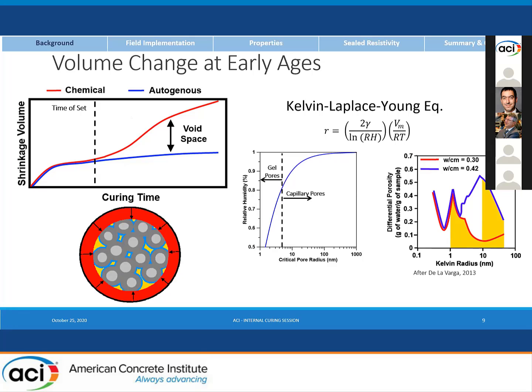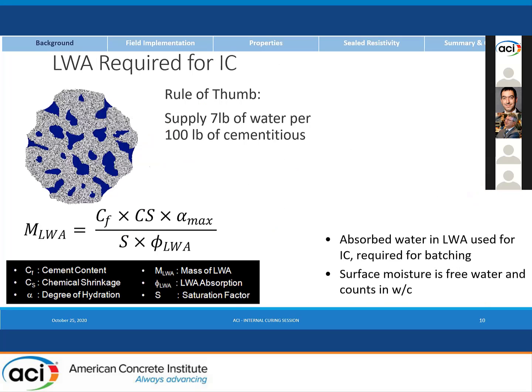And so if we look at a high water to cement ratio system versus a low water to cement ratio, and we lose the same amount of water, which is represented by the yellow shaded areas here, you'll see that in the low water to cement ratio systems, we're emptying out much, much smaller pores, and that creates a pore stress generation. So for internal curing, we're going to be focused here on the use of lightweight aggregates.